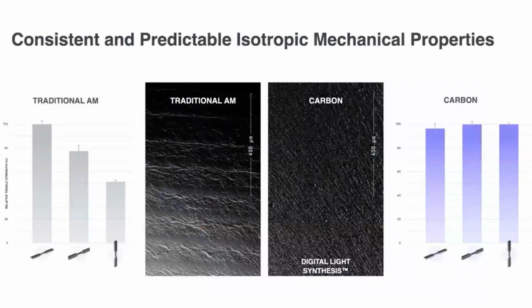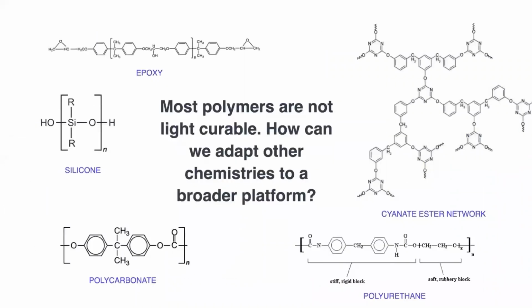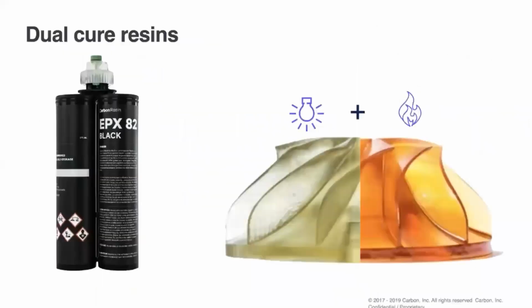And what happens is you get to see that with 100% UV curable systems grown continuously, the parts are isotropic. There's no detection of residual layers as in a traditional layer approach. As a result, the mechanical properties are invariant with the orientation of the part. And then the key thing is not only printing fast, but you also have to get great mechanical properties. And so we realize that 100% UV curable chemistry alone is not going to get you the parts that you want, because it's hard to get to the high chain entanglement or high molecular weight between entanglements that you really want in a polymerization.